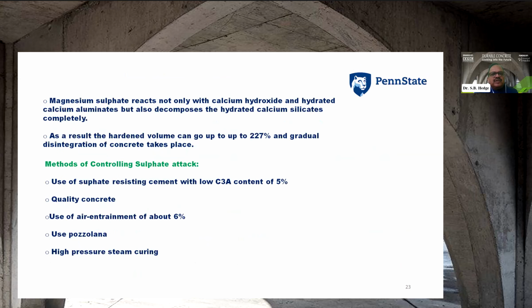The magnesium sulfate, which I mentioned, reacts not only with calcium hydroxide and hydrated calcium aluminates, but also decomposes hydrated calcium silicates completely. So you can see the white patches, which you can observe if it is attacked by magnesium sulfates. So how to control this sulfate attack?